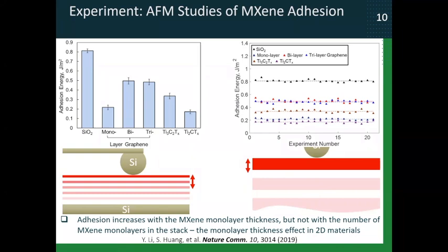And we have also discovered other effects. For example, adhesion increases with the monolayer thickness in the case of MXene, but not with the number of monolayers of MXene stacked in a van der Waals stack of these materials, okay? And also another interesting observation that we made in this paper in Nature Communications a couple of years ago, that the adhesion force between MXene and silicon, for example, is similar to the adhesion force between graphene and silicon, which makes it possible to fabricate heterostructures of these materials.